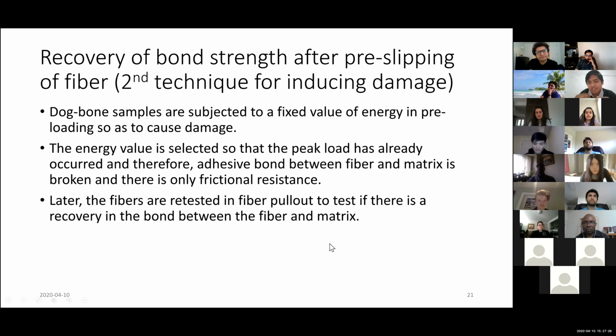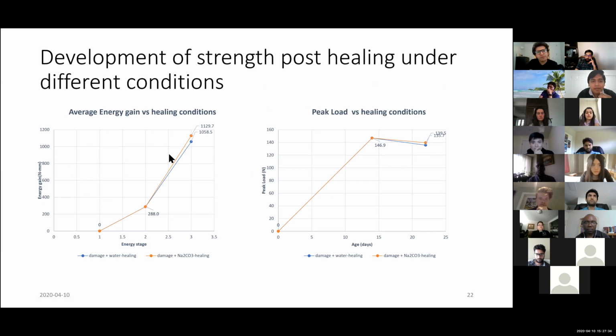And later they are tested again to see if there is a recovery of some form of bond between the fiber and the matrix. So this is preloading at a certain value of energy. So we can see that this is the preloading and this is after healing. After healing, there is a difference in between. Again, the sodium carbonate is slightly performing better in terms of fracture energy than this. And this is again for 6 samples each.